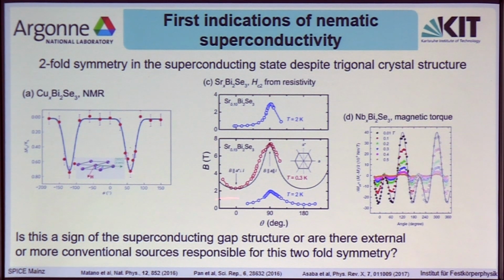Now, after the first reports, actually before the first reports of this twofold anisotropy were published, theorists were very quick in telling us that the underlying superconducting gap structure could be at the origin of this, and they termed this nematic superconductivity, as the trigonal crystal structure of the crystal is broken into a twofold one. However, of course, we would have to think about possible conventional sources or external parameters that could lead to such an observation.